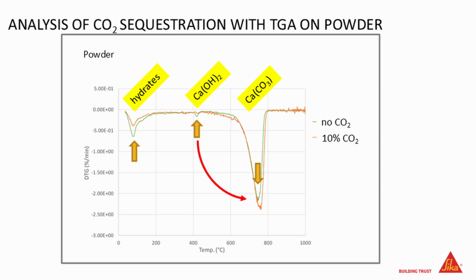So what we did is we made a thermogravimetric analysis of the powder before sequestration and after sequestration, and there you can nicely see what happens. So the calcium hydroxide we can carbonate. You see the small peak that's disappearing after the carbonation, and the calcium carbonates are increasing, and we can also carbonate some of the hydrates that you see. You see there is still potential of carbonating more, but this is how we measure it.